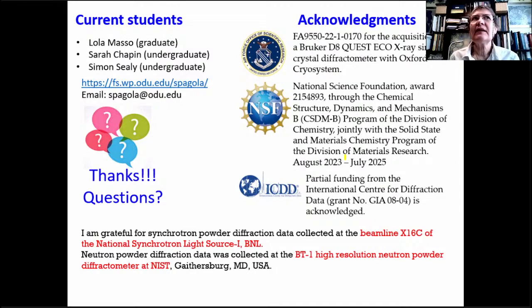I have not attempted aging. Basically, I guess I'm not 100% sure. I have exposed these reactants to vapors of those solvents, but without grinding. So in that case, after days of exposure to solvents, we obtain the products, the charge transfer complexes, but it takes much longer, days.